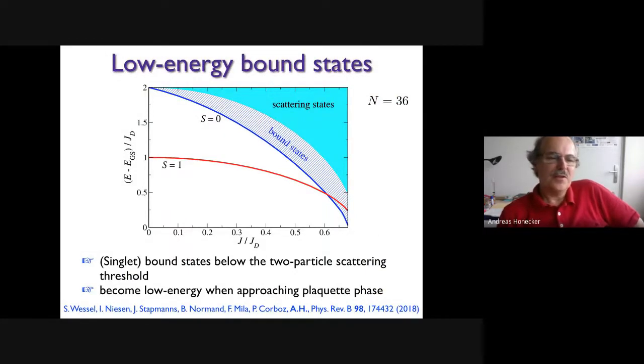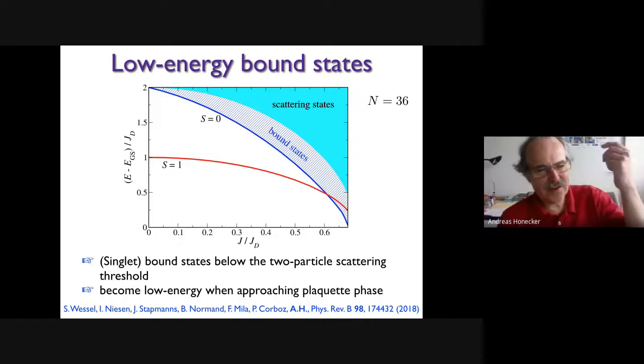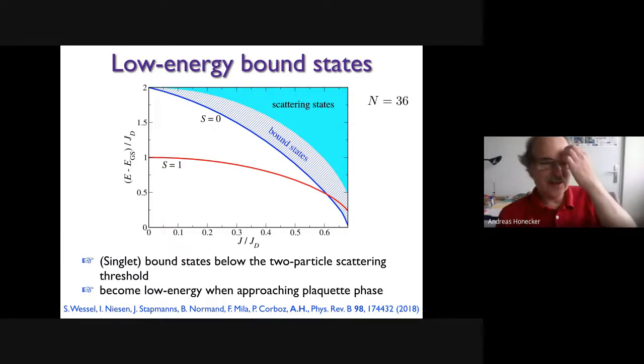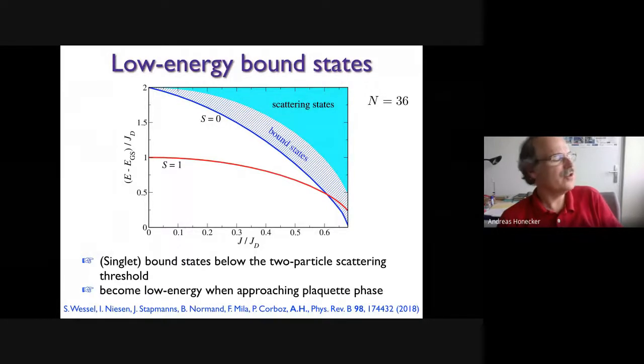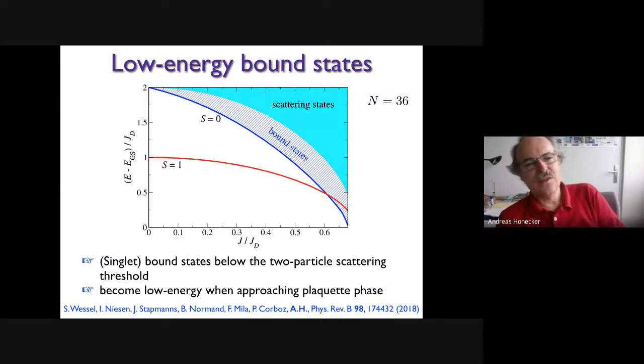If you look at the excitation spectrum, there's a single triplet excitation that you can trace from the isolated dimer on the left to the phase transition. Now you can form two-particle scattering states from the single particle, and so you get the two-particle scattering continuum that is sketched here in light blue. Now the point is, if you look at the spectrum, there's actually bound state formation. You actually get a singlet bound state that has lower energy than the two-particle scattering threshold. These singlets come down as you increase the coupling, and if you go to the transition to the plaquette phase on the right, they do cross below the single particle excitation. So you get low energy singlets that have an energy even below the single particle threshold.